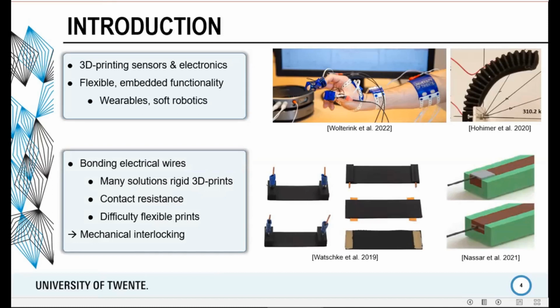And in the literature, a lot of solutions are proposed. So you can think of melting in some standard connectors, embedding wires or tape during printing, or applying silver paint or silver epoxy after fabrication. Or doing combinations where people embed wires and embed silver epoxy and then print on top of it to embed it. And all these methods heavily influence the contact resistance. So whatever method you pick, it will change your contact resistance for your samples. And actually, it's more difficult to do this for flexible prints because of the mismatch in material properties. And therefore, in this work, we propose to use mechanical interlocking for this.